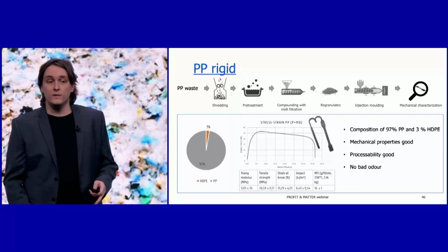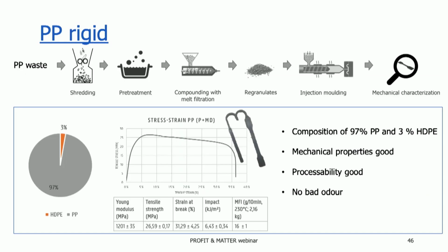The first stream is a PP rigid fraction. This waste stream consists of about 97% PP and only 3% other PE contamination. We started from the PP waste, but also from a fraction obtained after industrial melt filtering by ECO. The lab scale testing showed that the PP stream had good processing and mechanical properties, and no bad odor was remarked.